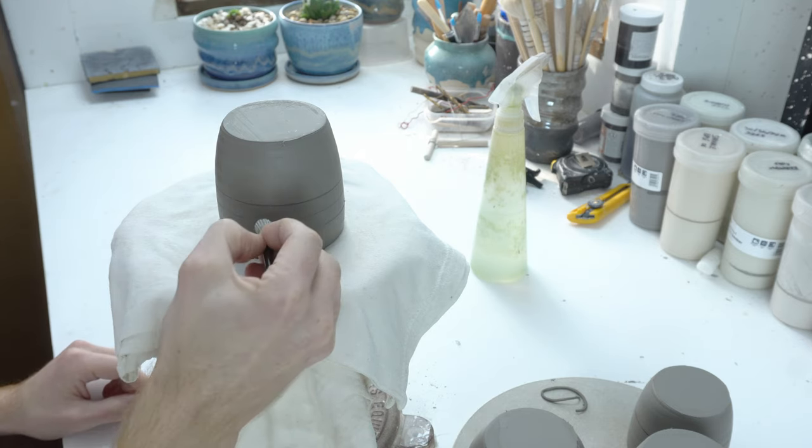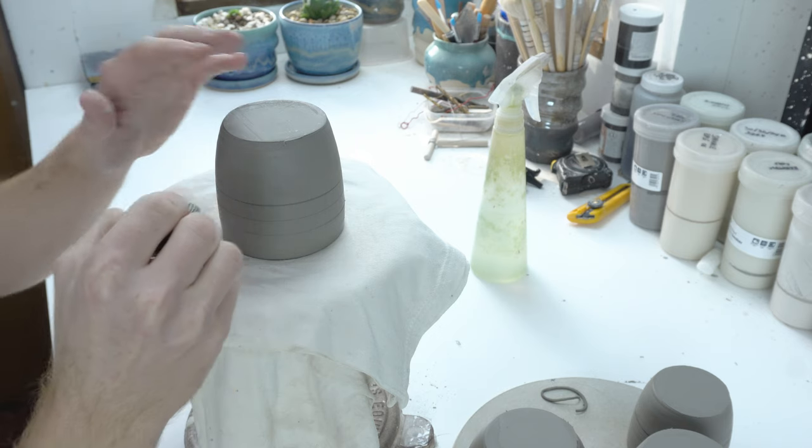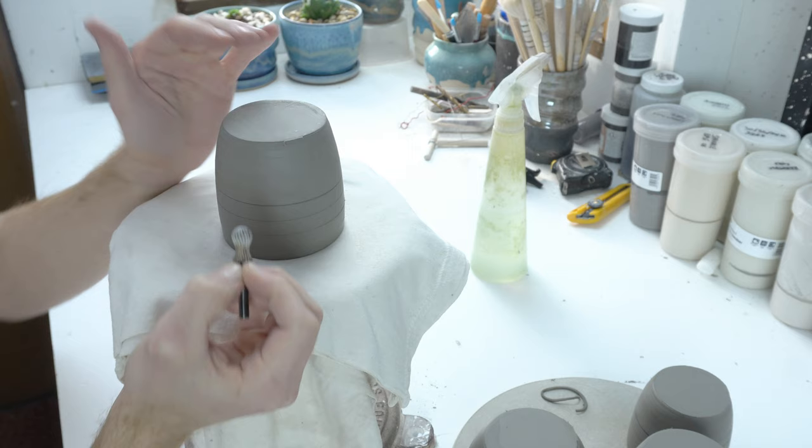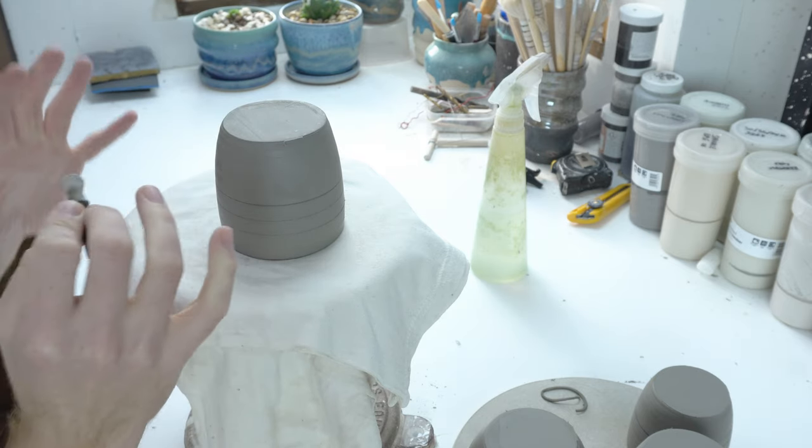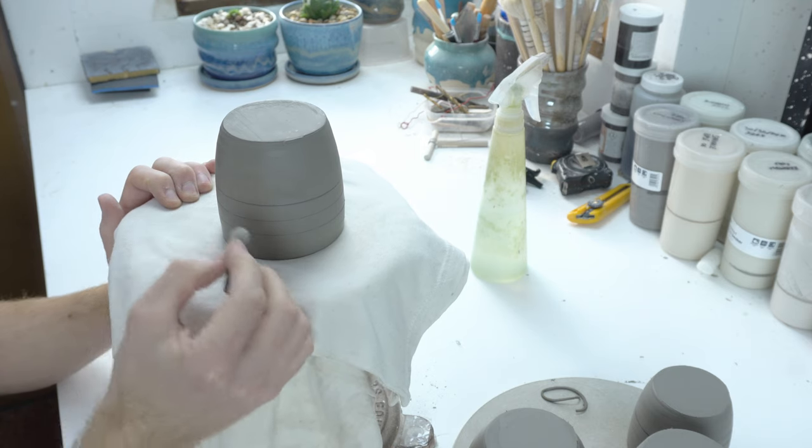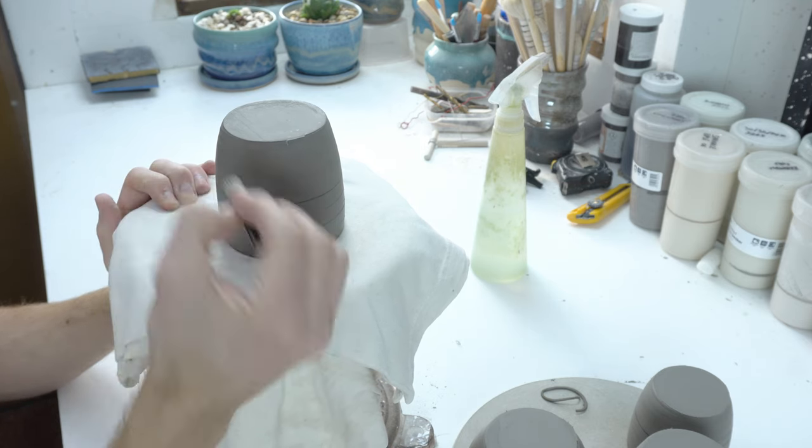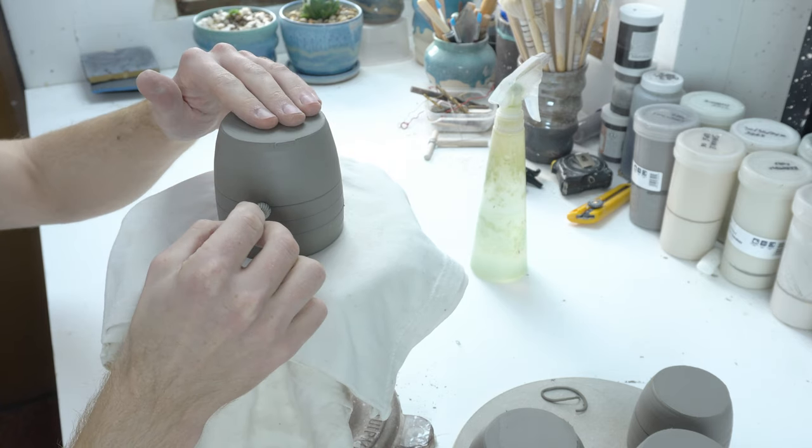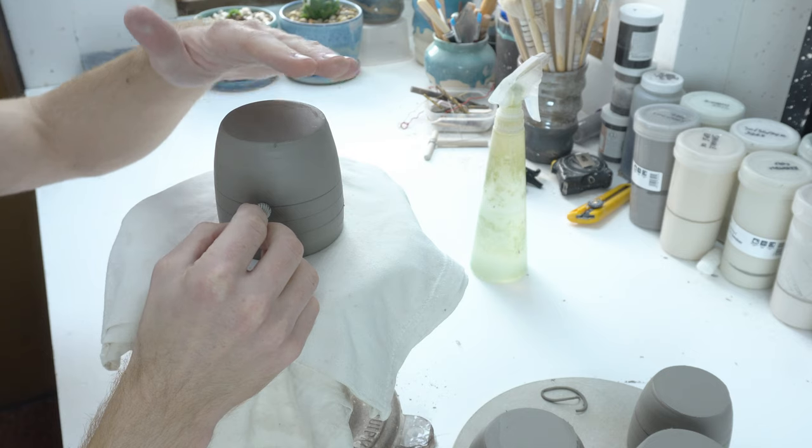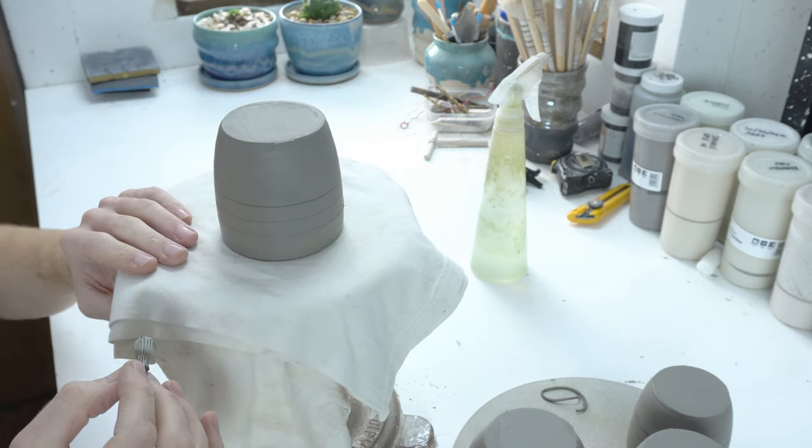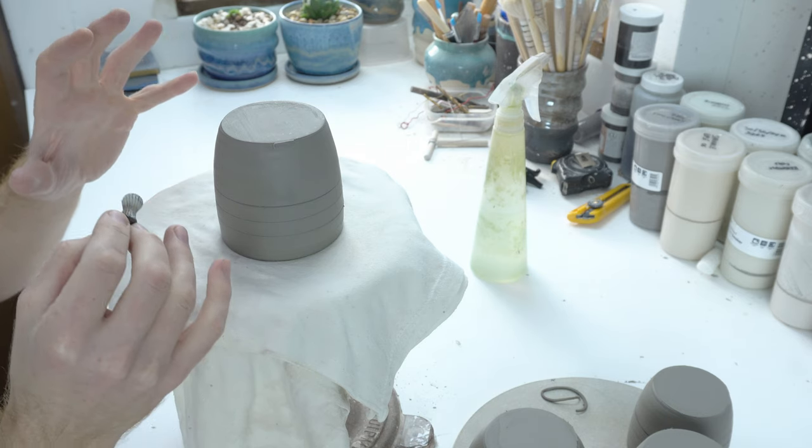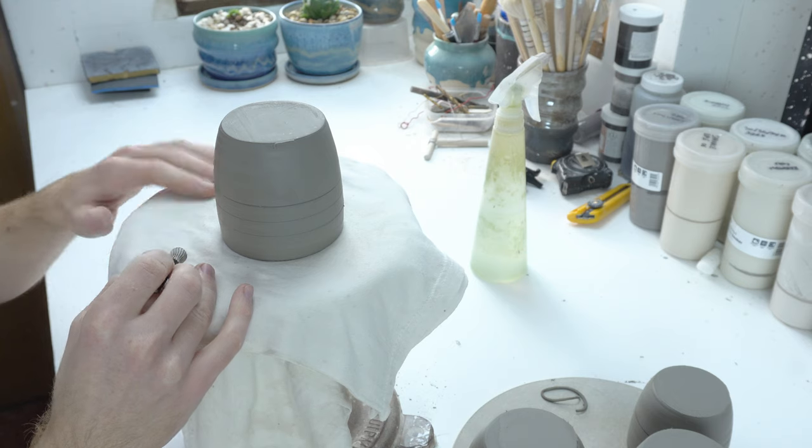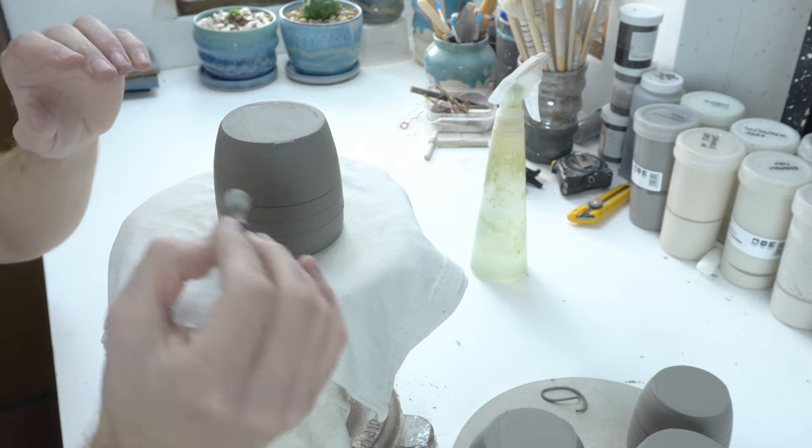You don't want to just push in because the clay ideally is going to be soft enough that if you did that you'd start to collapse the clay in. So what you want to do is push with less pressure on a smaller surface area. So I'll show you what I mean. And that is you put it centrally on the bit, you support the top, and I've got it on just an old t-shirt. That's twofold. It protects the rim but also because it's difficult for the piece to slide over.